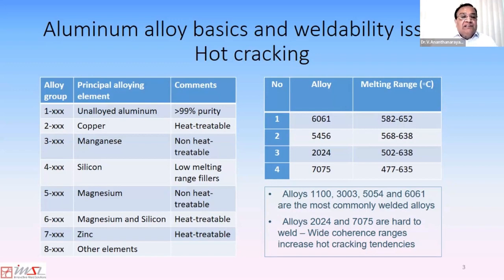aluminum alloys. The 6000 series are heat treatable to high strength and are used in body panels for many vehicles, such as the Ford F-150 here in Detroit. And what differentiates them, as you see on the right side here, is the melting range of the alloy. If you see the alloys 6061 and 5456, the range of temperatures between the solidus and the liquidus, as shown in this slide, is roughly around 70 degrees Celsius.